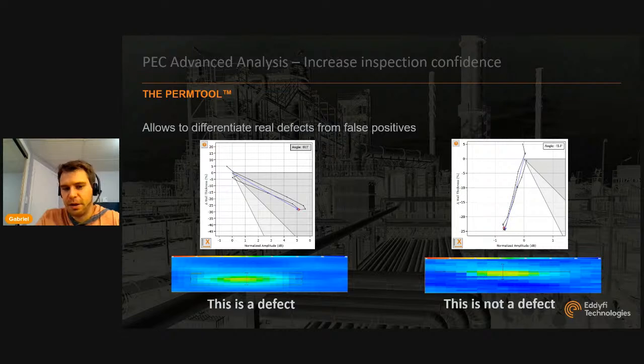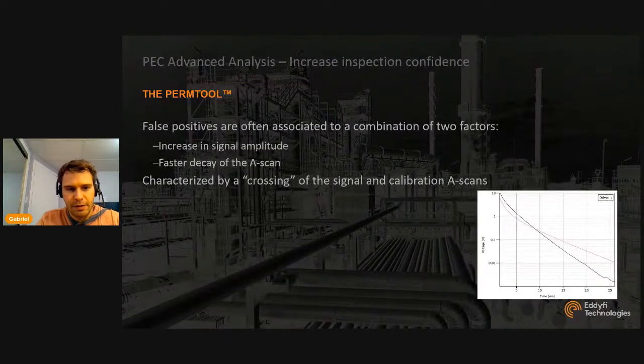This is suspected to be a hard spot, so that was a bare pipe, no insulation, no wall loss measured with UT, but when you scan with PEC, and you could get the same thing with a different electromagnetic technique, you're seeing a change in properties. So there's a change in conductivity or permeability that's affecting the PEC sizing. But with the PERM tool, we're showing a different signature.